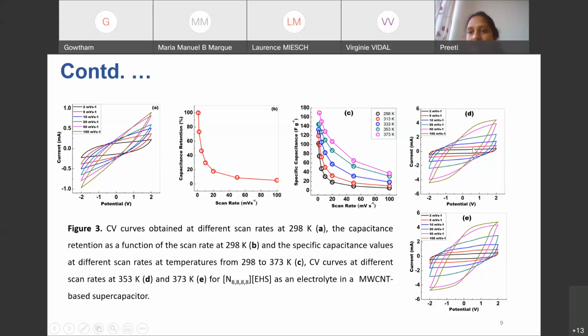And if you can see here, this D figure is at around 80 degrees centigrade, and this E figure is at 100 degrees centigrade. You can see that up to 100 millivolt per second, the rectangular shape remains the same. And similarly, we observed in the specific capacitance values that at room temperature, the values are very low with increasing scan rate. But when we increase the temperature, we can reach from 100 up to somewhere around 170 farad per gram,